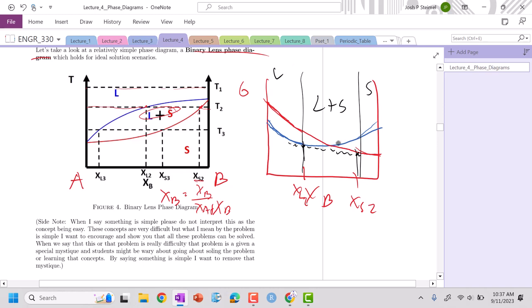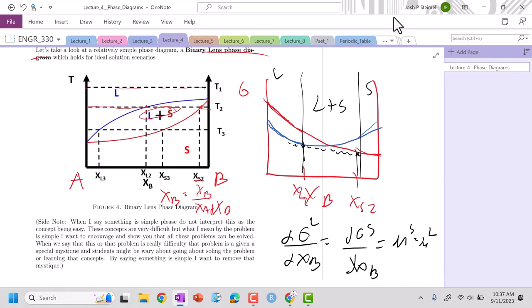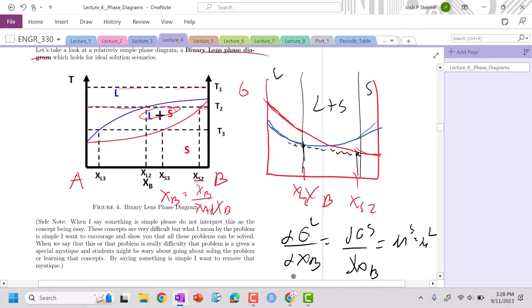And the common tangent is basically dG/dxB are equal in both of these phases of the material, of liquid and dGS/dxB. So that is basically the same thing as saying our chemical potentials are equal as well. So if the slopes are equal and we have a common tangent, we will have a region where we are both simultaneously liquid and solid.